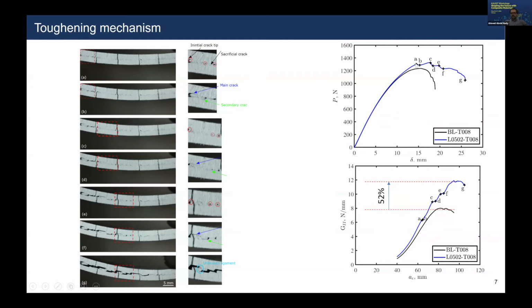The crack initiates at point A here, and once the crack initiates, it propagates up to point B. At point B, a secondary crack propagates at the sacrificial crack, which arrests the crack up to point C, and then the situation is repeated at each sacrificial crack, reaching point G. Even at point G, which is a very large displacement, 25 millimeters, still unbroken ligaments can be seen here, which connect the upper and lower adherends. This results in a large toughness improvement, a mode 2 toughness improvement of 52% in this case.